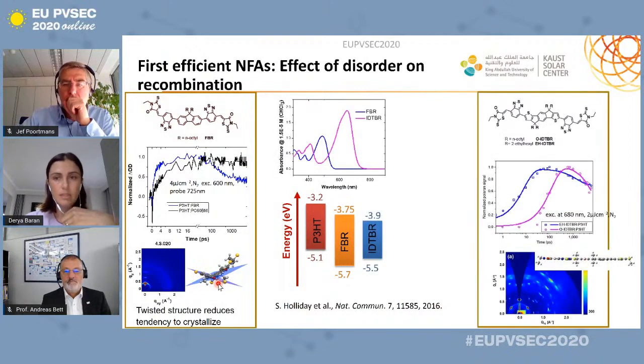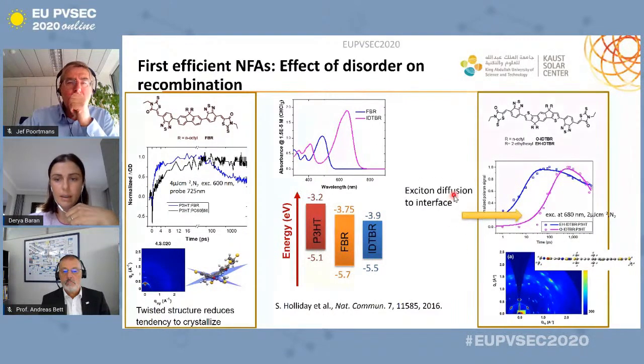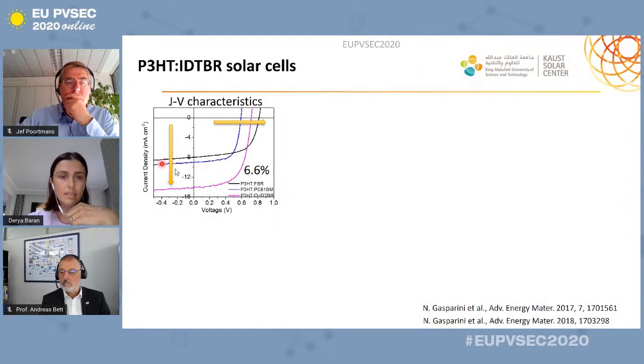And then the group I was in, Professor Iain McCulloch's, actually synthesized this coplanar IDTBR structure, as you see here as well, which was beautifully planar. And then you could see that it tended to aggregate and create beautiful crystals. And in the heterojunction, we have seen that there was a long diffusion of excitons to the interface, which is what is more expected from the OPV bulk heterojunction. And these characteristics allowed about 6.6% efficiencies. And at that time, this was the highest for P3HT solar cells.